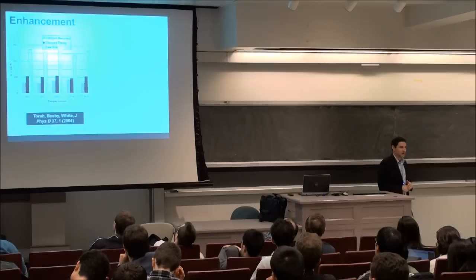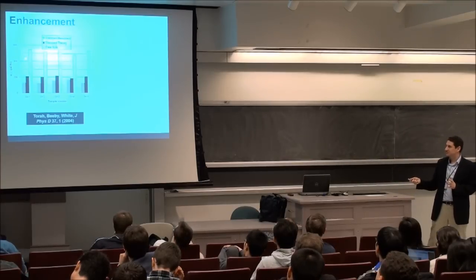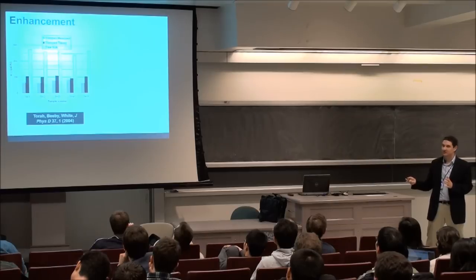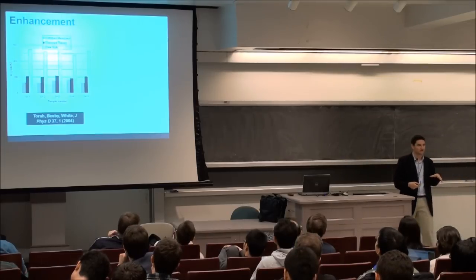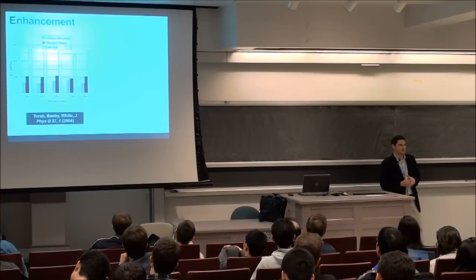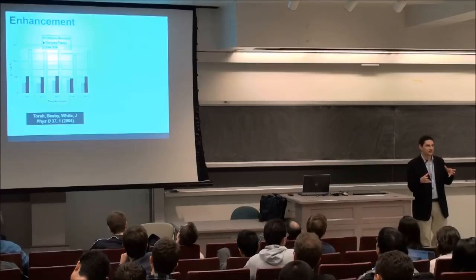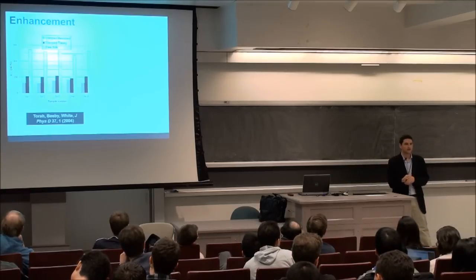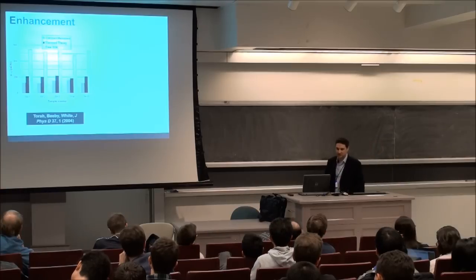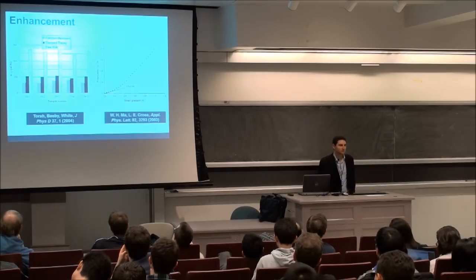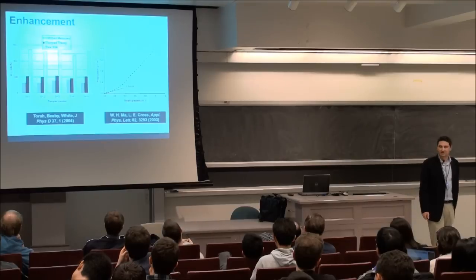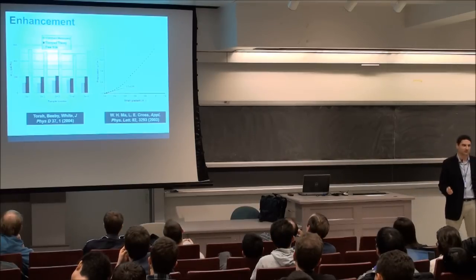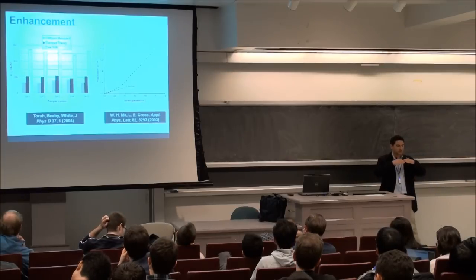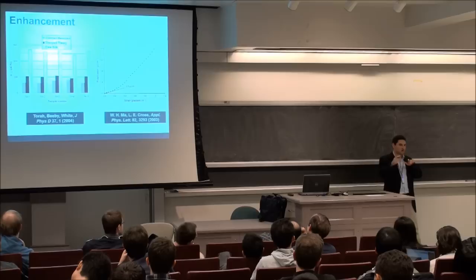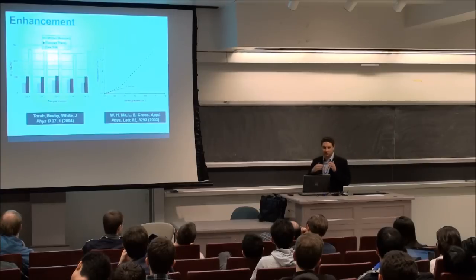So the first thing is we looked in literature. We actually saw that in clamped PZT, this is from 2004, you actually get significantly reduced piezoelectric charge constant compared to freestanding PZT because of this clamping effect. And in fact, this is why bulk PZT has a higher piezoelectric charge constant than thin film PZT. So that's one explanation. I think this is the least interesting explanation. Another explanation, which I think is incredibly fascinating, which I'm going to talk about for the rest of our time here, is this concept called flexoelectricity, the flexoelectric effect, which basically means when you take a wafer and you bend it, you basically form an expansion strain at the top and a compressive strain underneath. Okay, so you actually can create a polarization.